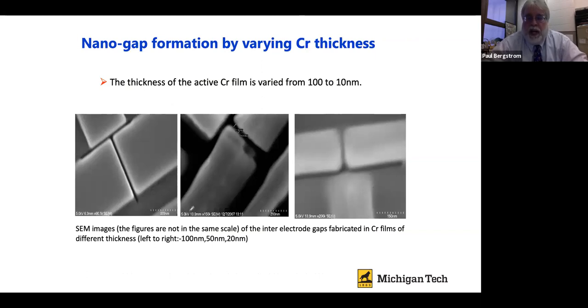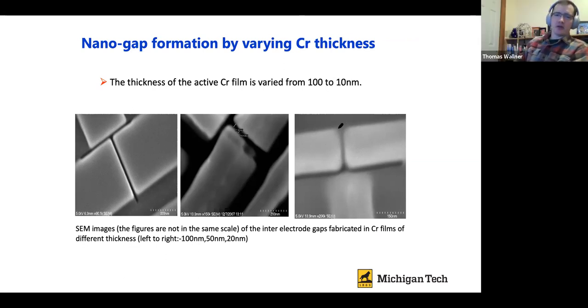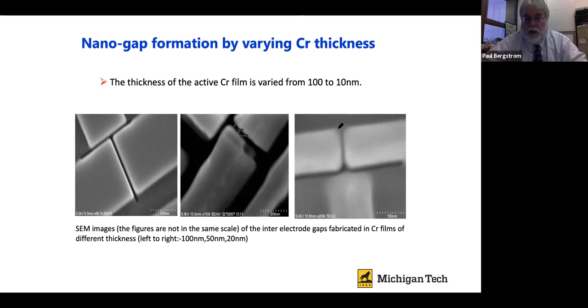So doing some understanding of that energy tail, one of the subsequent students, Manoranjan Acharya, did some very good work to understand that if we now etched through an additional layer, we would be able to produce the features we wanted in the underlying layer down to about sub 20 nanometers. And then we remove that sacrificial layer on top and we're left with the features that were as narrow as we could get. So these structures were roughly about 200 nanometers across. But these gaps, the narrowest gap that he was able to optimize for was about 17 nanometers. That was the smallest feature that we were able to produce in the structure. But that showed us our limit for etching.